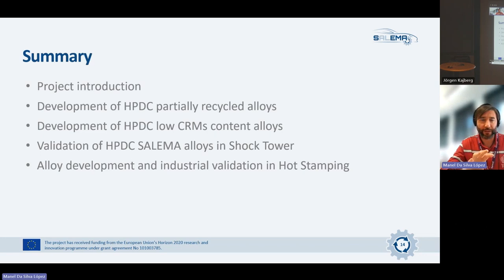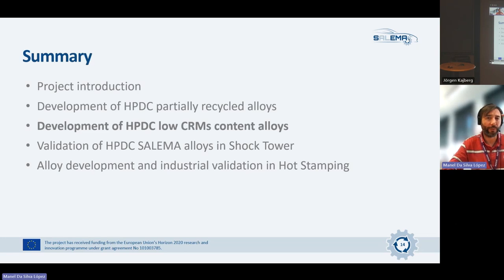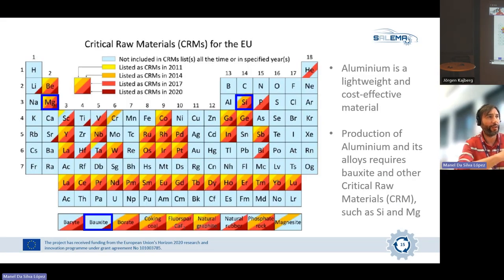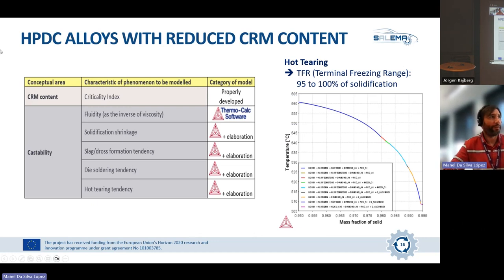Okay, so that was regarding the development of partially recycled alloys. I will shortly explain also the procedure we follow for formulating alloys with lower critical raw material content. The first thing we did was go into the list of critical raw materials posted by the European Commission, and we developed a way to calculate the criticality of these alloys. We have a criticality index, where we weight the composition of the alloy and how critical the different elements are. Then we evaluate the castability of the alloy with ThermoCalc software, by thermodynamic simulation, and in some cases elaboration.